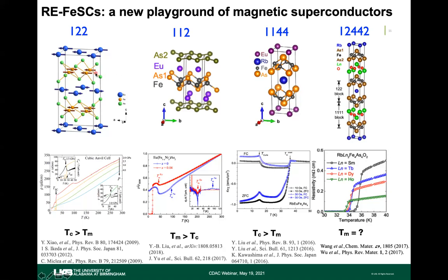iron, some of the d orbitals actually contribute to the superconductivity, and some other d orbitals contribute to this RKKY interaction, mediate the RKKY interaction on the europium. So with that, it contributes to a magnetic ordering in the europium lattice, and also superconductivity in the iron arsenic layers.